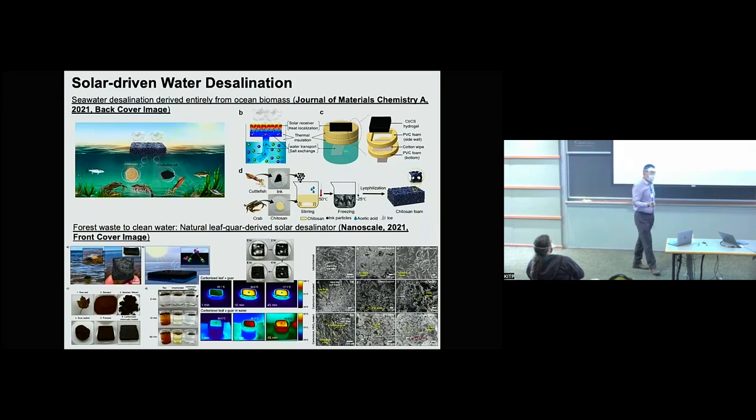We simply purchase food-grade squid ink, cuttlefish ink, and in our lab we dry that, and also we use a ball miller to make natural carbon nanoparticles ourselves, and we are able to obtain carbon nanoparticles with an average size of 20 nanometers out of cuttlefish ink. We mix it into the chitosan as a skeleton. We make a hydrogel-like material. I'm going to show the result later in the next 4 slides. And we also achieve a high water evaporation rate, up to 4.6 liters per meter square per hour, with the use of these low-cost ocean waste materials.